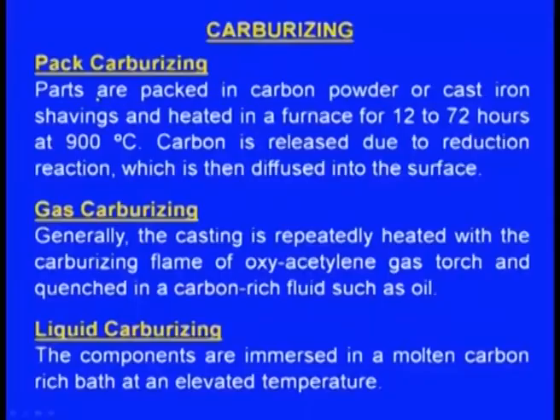In pack carburizing, parts are packed in carbon powder or cast iron shavings and heated in a furnace for 12 to 72 hours at about 900 degrees centigrade. The component is packed inside the carbon powder or cast iron shavings. Carbon is released due to a reduction reaction, right? Then that carbon diffuses into the surface and hardens the surface. So that is pack carburizing.